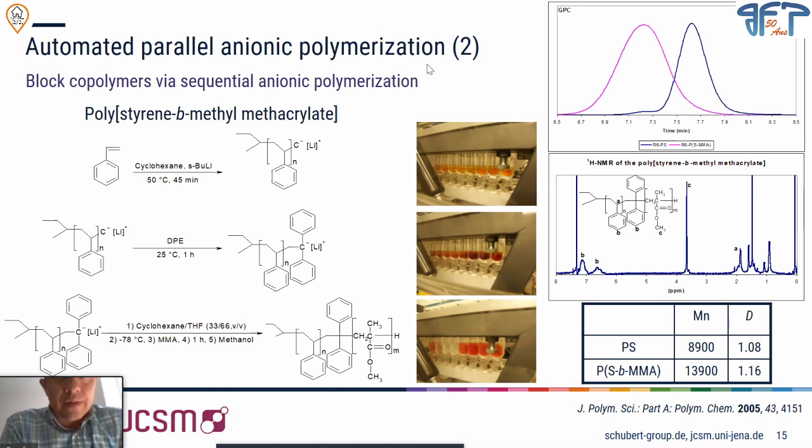But once you incorporate the second monomer, the system is very reactive. So you have to lower the temperature quite low. In the literature, it's reported to -78. But in this case, we set up the machine, and I must say we were very much at the limit, because the recirculator goes to -90.